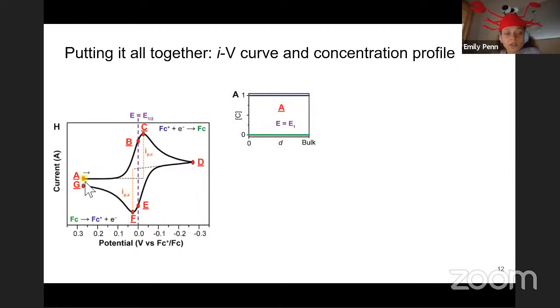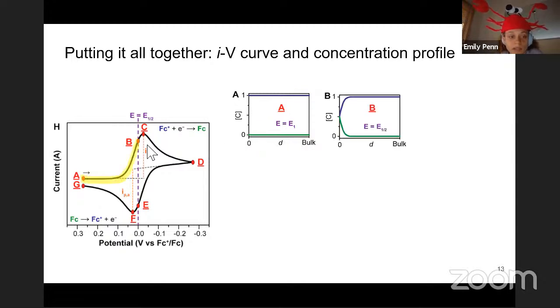So now that we went through the diffusion equation and looked at the concentration profile, we can look at how the concentration profile aligns with this current shape, just to put it all together. At A, at the start of your experiment, this blue line is the concentration of our reactant, and you can see that everywhere the concentration of the reactant is 1, and we don't have any of our reduced species. And then at B, as we reach this E1/2 potential, our species are in equilibrium. So we have an equal concentration of the oxidized and reduced species at the electrode surface.